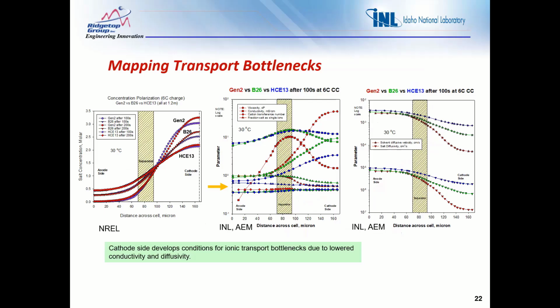So taking that same plot that we just saw, and here it is on the left-hand side, we can march along each of these concentration polarization curves and find the electrolyte property at that point. And that's what we've done. We've plotted different transport properties in the middle panel here, ranging from viscosity, conductivity, cation transference, and also the fraction of salt as single ions. We'll just look at the conductivity values, which are the squares.